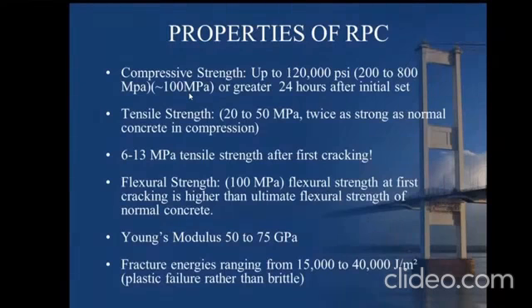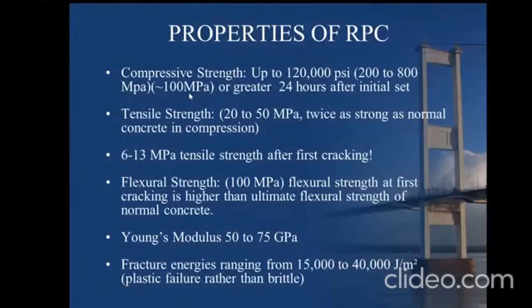Rather, we embed fibers inside the matrix of the reactive powder concrete, and the thickness of the sections that we are building using the reactive powder concrete is very thin. I would give you an example. A bridge girder was designed with an M60 concrete, which resulted in 1.5 meter depth of the girder. When it was replaced with reactive powder concrete, it was only 30 centimeter. So just imagine the reduction in size of the sectional member when reactive powder concrete comes into place.